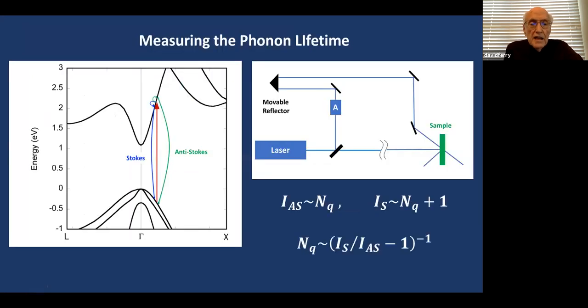Okay, so how do we measure those distribution functions and lifetimes? We do it with Raman scattering, okay? So what's Raman scattering? Here's my photon coming in, that's the red line, creates an electron hole pair, and they can recombine either after absorbing a phonon, which gives you the anti-Stokes line, which has a higher energy, or by emitting a phonon, which gives you the Stokes line, which has a lower energy.